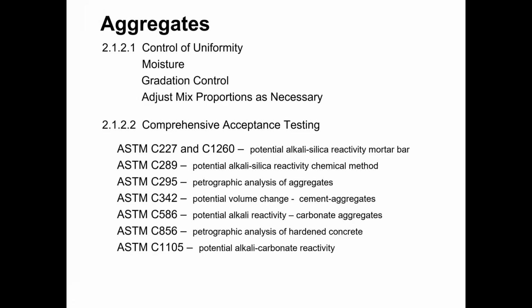Generally, we want to have control on the moisture in our aggregate. We can do that in a couple of different ways. One is we can control the environment of the aggregate. So we can keep aggregates covered, we can keep them sprinkled to maintain a consistent level of moisture. Another thing that we can do is we can do regular testing of the moisture content and then make adjustments based on the actual moisture content of the aggregates.